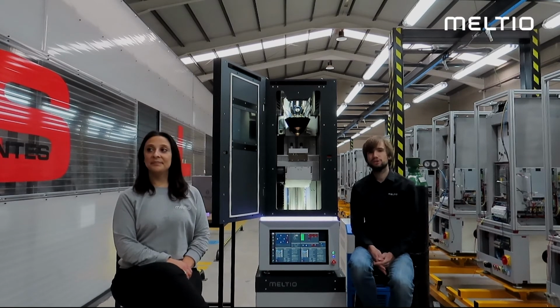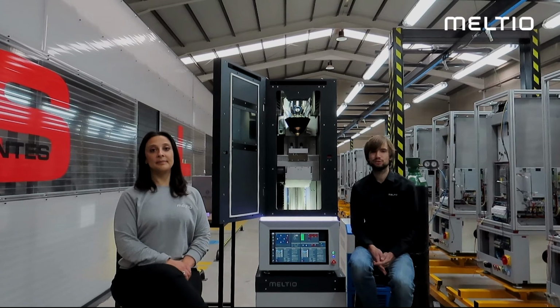In general, our printing process using pure metal wires as feedstock achieves very good material properties with densities greater than 99.99% and part properties that typically exceed those of castings and get very close to those of forgings. Critical for the success of our mission to achieve mass adoption of this technology is our material strategy, where we allow the users to choose between Meltio supplied materials that are delivered with fully qualified printing parameters or third-party materials that can be sourced locally from a very large market of welding wires.